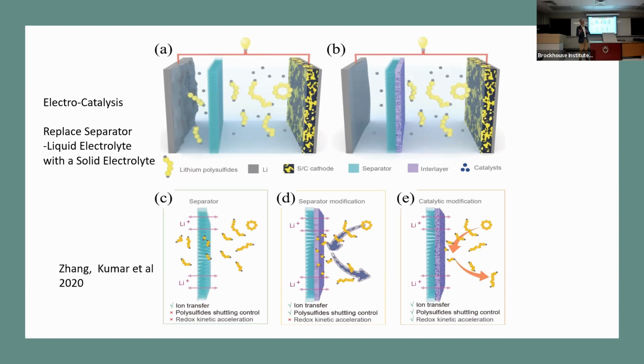Yeah, so that's high temperature. It's the kind of lithium ionic materials that sinter at about 1100 degrees centigrade, so you can't incorporate that into the current assembly line. Yeah, but if you make that as your substrate, then you have to make it thick. You can't make 10 microns of it. There is no method, but it can't be freestanding.